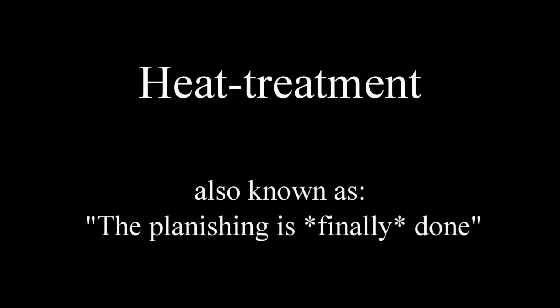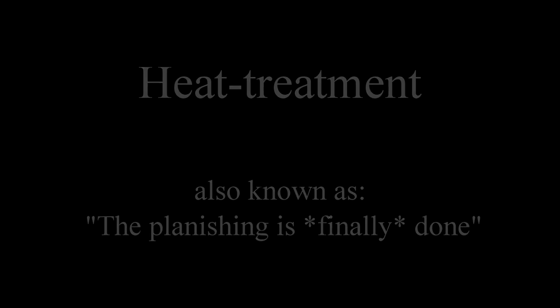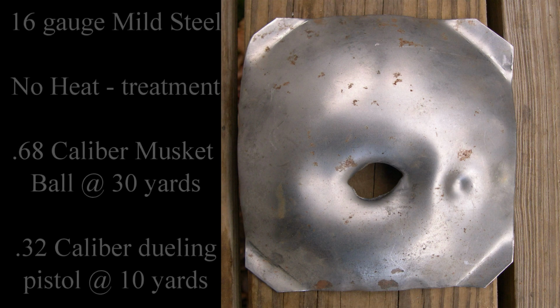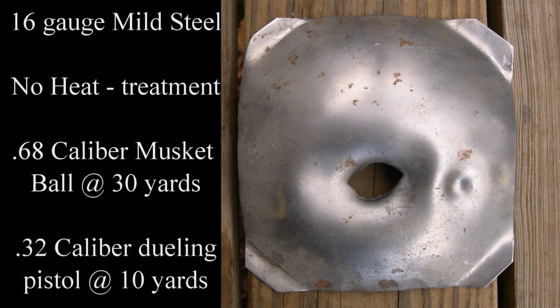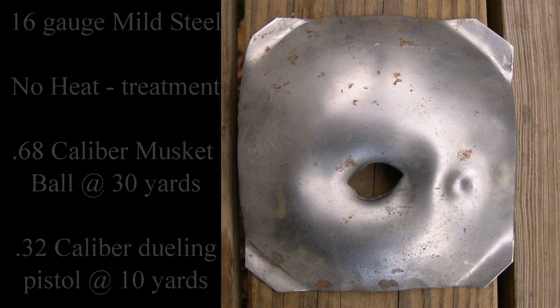Heat-treated carbon steel, also referred to as spring steel, provides tremendous benefits over mild steel and even stainless steel. To demonstrate, these test plates were shot with a black powder musket and dueling pistol. This mild steel plate was dented by the dueling pistol in a fashion very similar to many period proofing marks, but the musket ball goes right through.